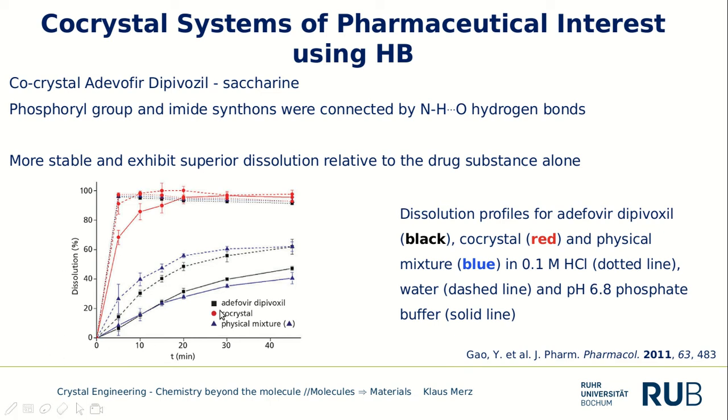What we directly see, the first impression, is that very rapidly, in some minutes, you have a high dissolution of the co-crystal. Very nicely, independent of the solution. You see it here as an HCl solution and a phosphate buffer solution and so on. Independent of the solution, versus the mixture, very rapid dissolution of the co-crystal.